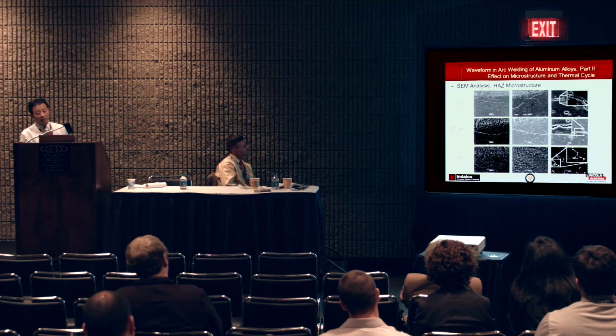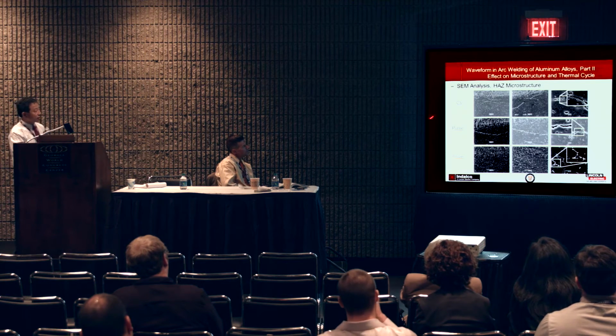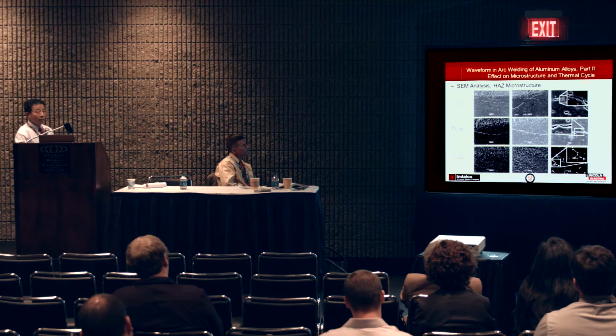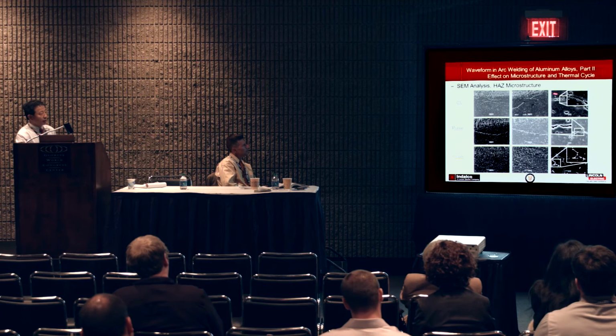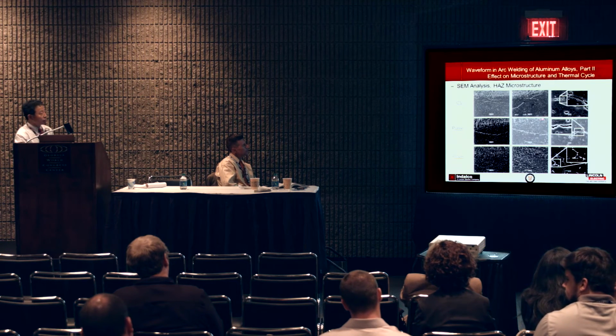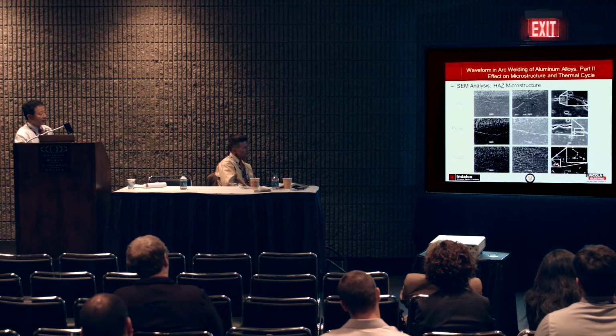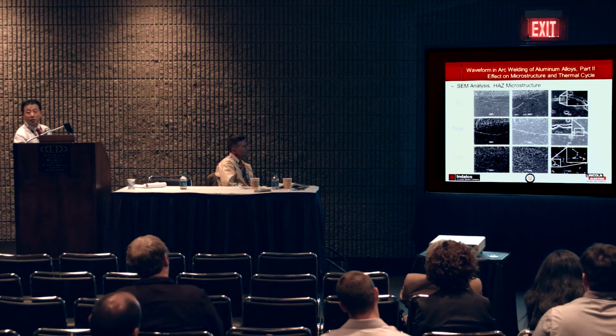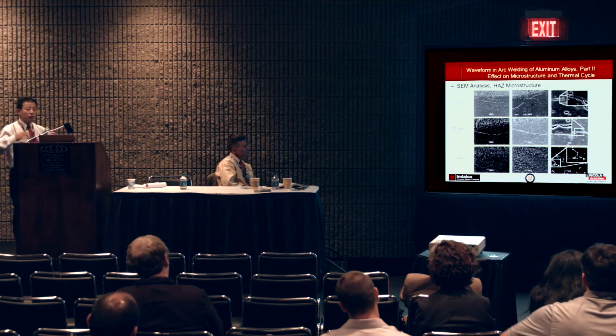And I further did some investigation using SEM, the secondary electron beam. And you can see that I got some small liquation cracking in my heat affected zone, which I observed with my CV and pulse mode, but we didn't see that kind of liquation with the power mode. However, we see very nice things. We observe some precipitate showing up in my heat affected zone close to my fusion boundary.